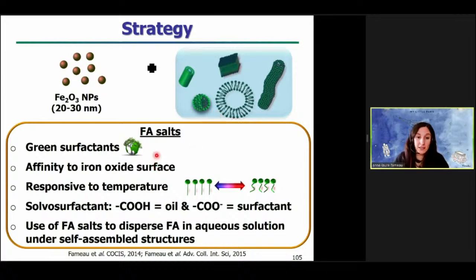Because they are green surfactants. They have some affinity to iron oxide surface. They are responsive to temperature, as I showed you in the previous part of my talk, due to the transition between the alkyl chain in gel state and the fluid state. And they are solvosurfactants, that is to say, when the fatty acids are under their carboxylic form, above their melting temperatures, they behave like oil.